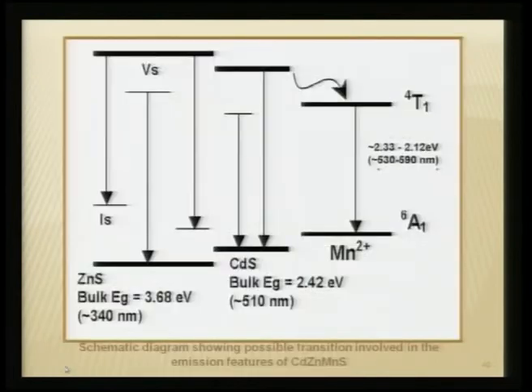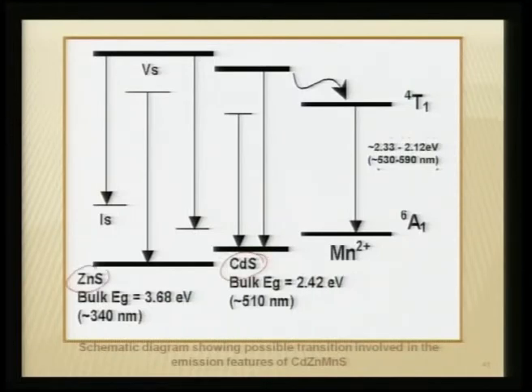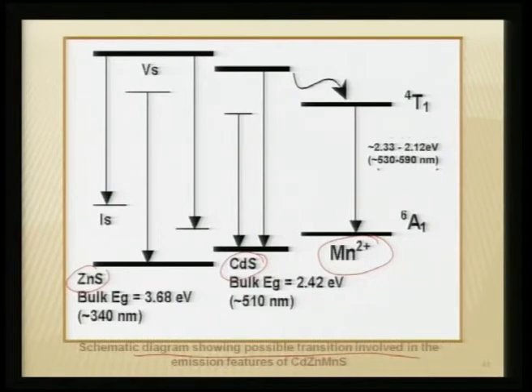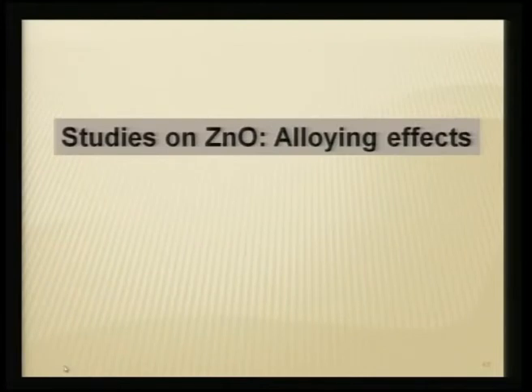The band gap picture: ZnS is the wide band gap host; making a solid solution with CdS alters the band gap. Adding Mn²⁺ as a co-activator induces a broad emission. The schematic diagram shows all possible transitions involved in the emission features, including the broad emission peculiar to the Mn²⁺ crystal field environment in this Zn-Cd sulphide system.